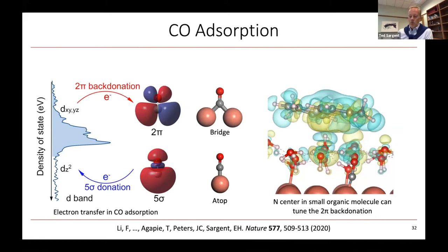And so our Caltech friends prepared a library of N-aryl pyridinium salts. And then we sought to tune the chemical environment by putting different electron donating and accepting groups to tune the electron density on the nitrogen so that the nitrogen center, which is in charge of the electron donation, could be tuned.